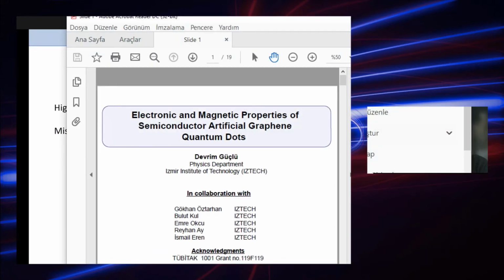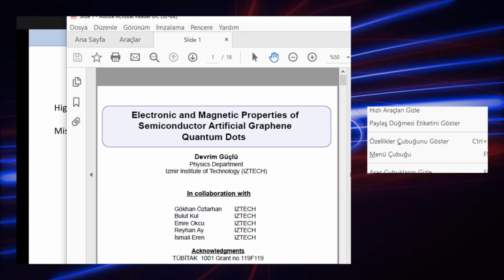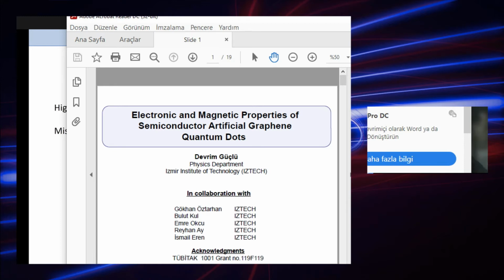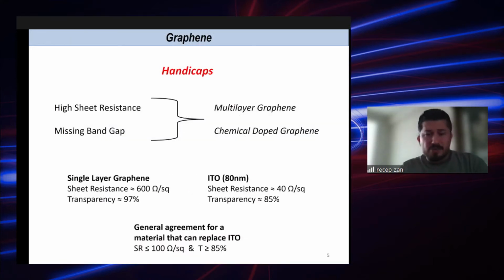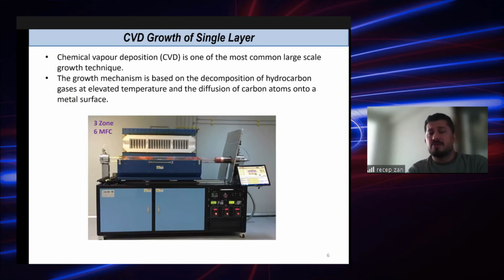We are okay with the transparency, but the sheet resistance of the graphene must be reduced to be used as a transparent conductive electrode. In general agreement, for graphene or any material to be used as a transparent conductive electrode, sheet resistance should be around 100 ohm per square and transparency over 85%. So what we did in our case, we grew graphene in a CVD system. We have a CVD system with 3 zones attached with 6 MFCs, and we are able to control the 3 different furnace zones with different temperatures. We use methane as a carbon source, and we grow all the graphene on copper foil.